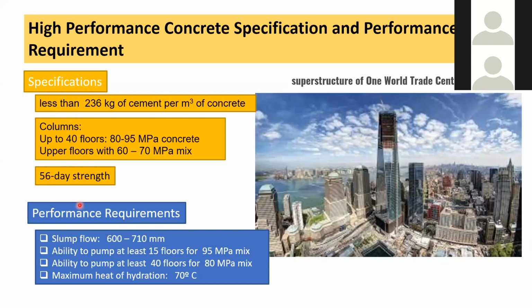But performance requirements are given. There was a slump flow requirement of 600 to 710 millimeters. Of course, it's flow, not slump. That is, when you do the slump test, it should meet a flow requirement of 600 to 710 millimeters. These are the important criteria. The concrete should have the ability to pump at least 15 floors for the 95 megapascal mix, and the concrete should have the ability to pump at least 40 floors for the 80 megapascal mix. That means this is a fresh performance requirement that is placed on concrete. Whatever concrete comes to the site, it should be able to meet this requirement.